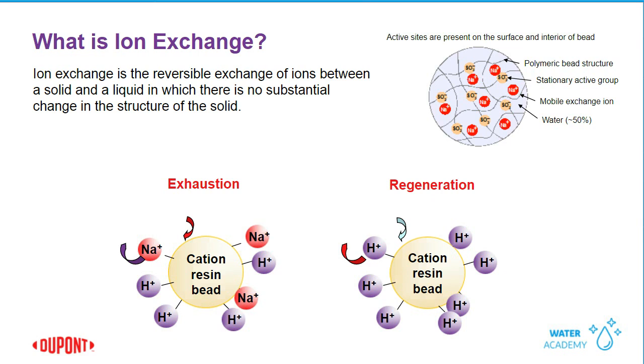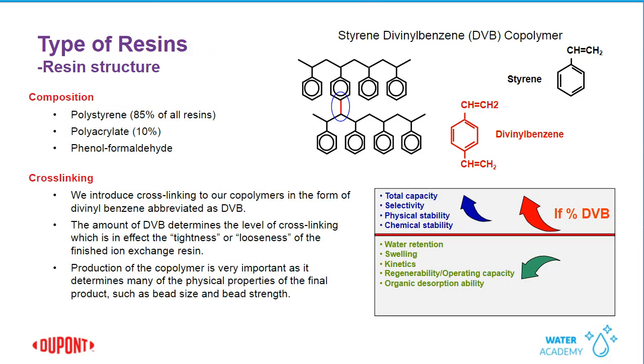Okay, so let's talk about what the resin beads are made of. Almost all of the resins in the industrial water market, or I shouldn't say all, I should say 85%, which is a large portion, are made of styrene. About 10% of the resins have an acrylic polymer bead structure, and we also have a phenol formaldehyde chemistry. We add cross-linking to these beads with a compound called divinyl benzene. And in the top right-hand portion of the screen, I'm showing pictures of styrene divinyl benzene copolymer. So on the right-hand side, you can see the structure of the styrene and the divinyl benzene monomers. So we polymerize these together and make long chains of styrene that are cross-linked with divinyl benzene.